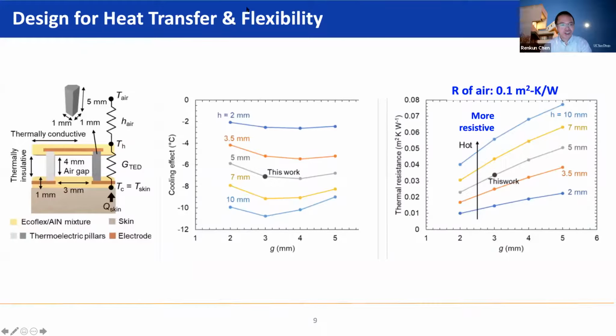I will not show all the details, but basically you can see the geometrical design of this device is very important. So here we can see this cooling effect. So this temperature goes down. So -12 means it's more cooling, as a function of G. Here G is this parameter of the spacing between the pillars, like 3 millimeter. And then there's also H, which is the height of this pillar. So for this particular design, we have a height of 5 millimeter and a spacing of 3 millimeter. So we can achieve a cooling effect around 7 degrees Celsius, the maximum cooling based on our simulation.